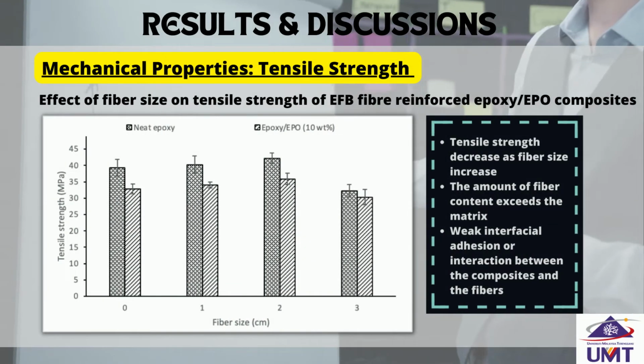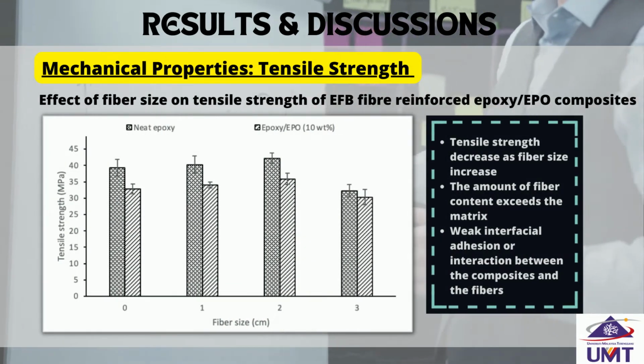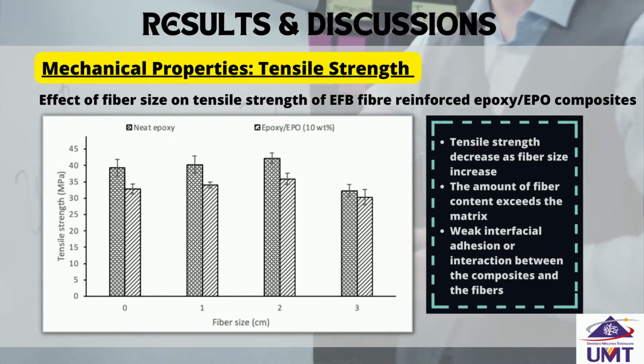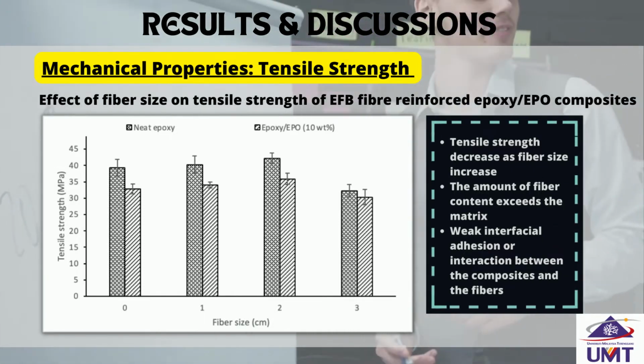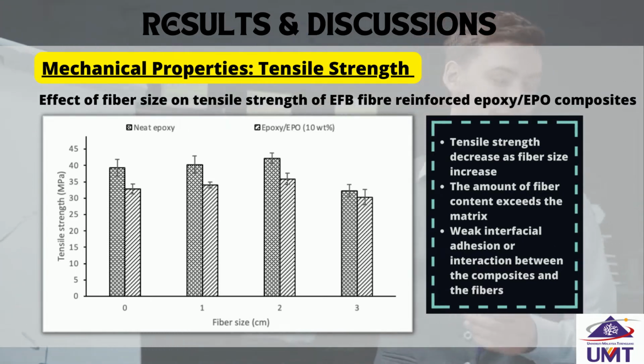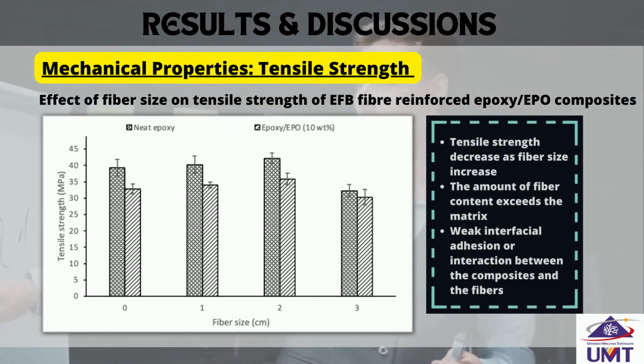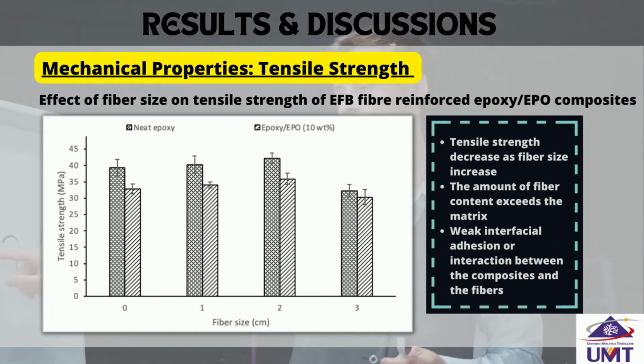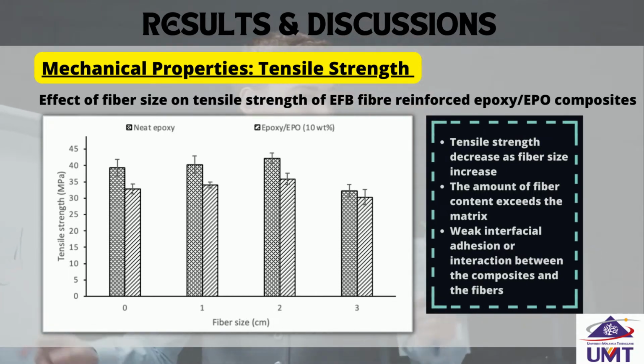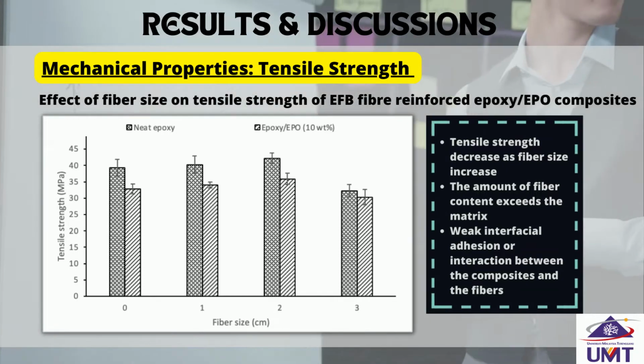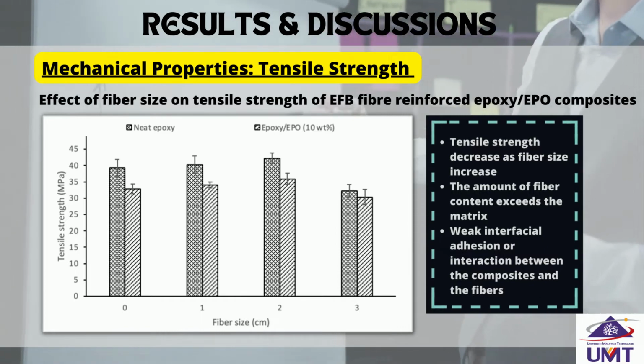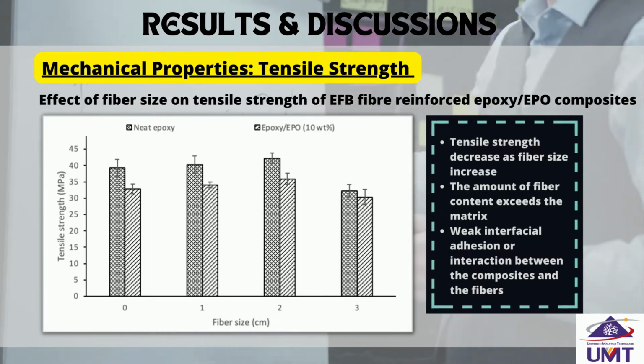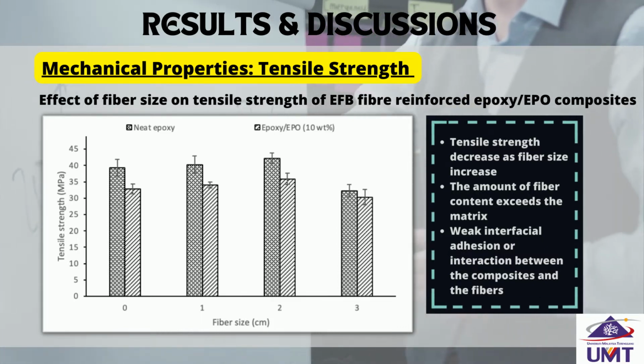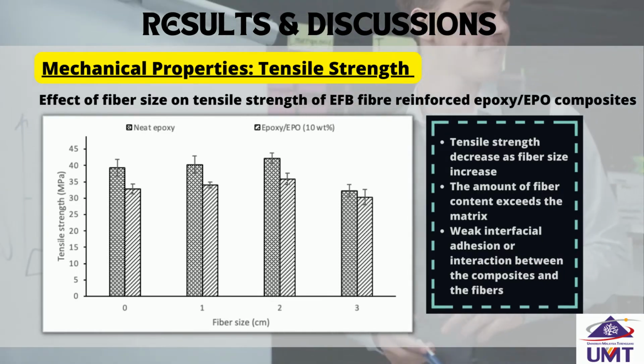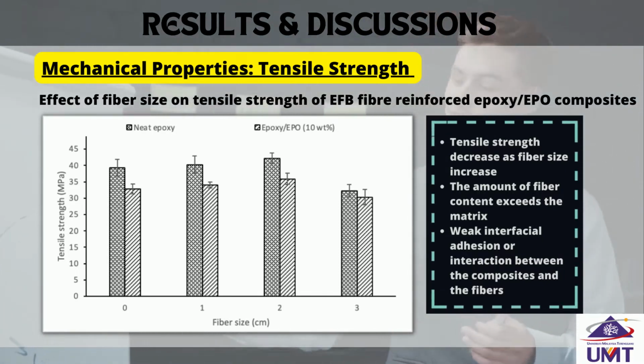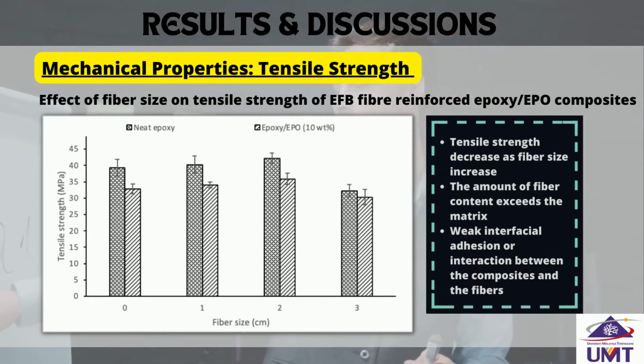Results and discussions for mechanical properties, tensile strength. Those are the effects of fiber size on tensile strength of EFB reinforced epoxy EPO composite. The tensile strength of both neat epoxy and epoxy EPO composites improved until it started to decrease after it exceeded 2 cm fiber size. This situation happens as the fiber-matrix adhesion weakens and the amount of fiber content exceeds the matrix, so the properties deteriorated.